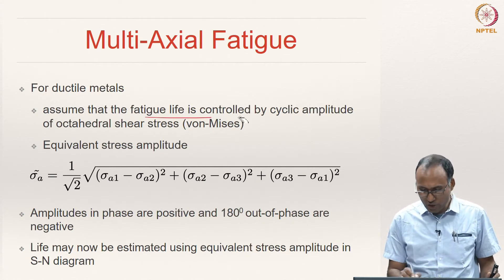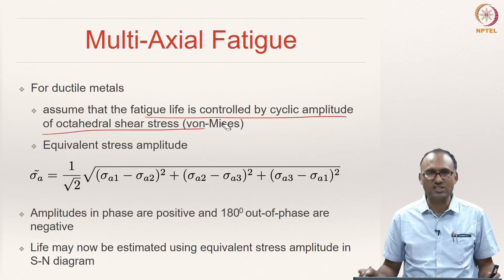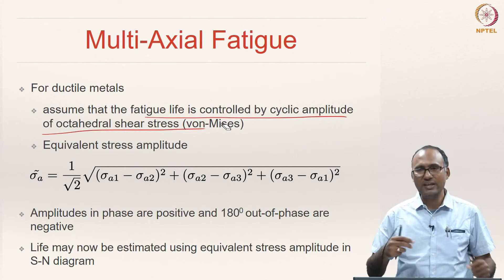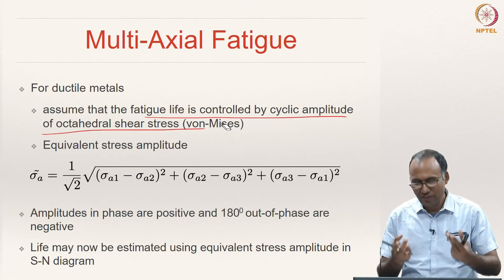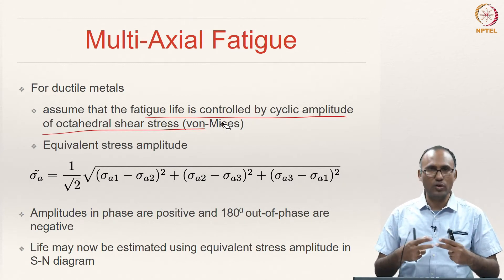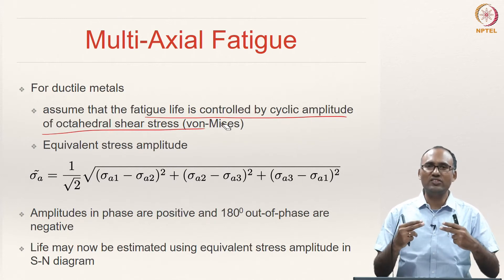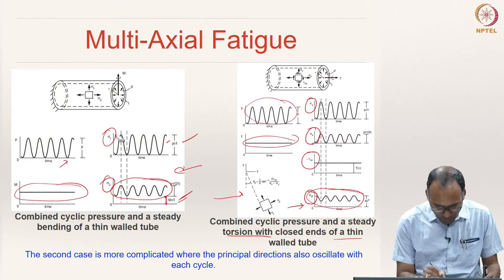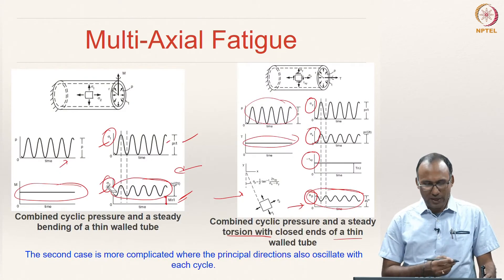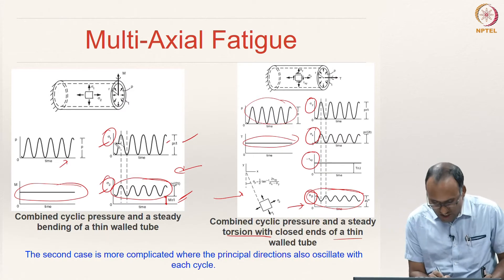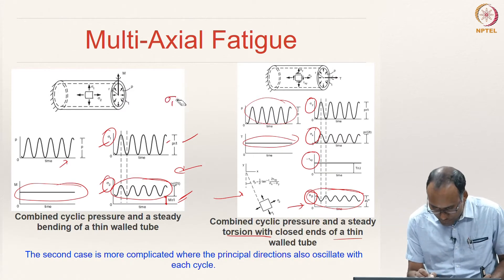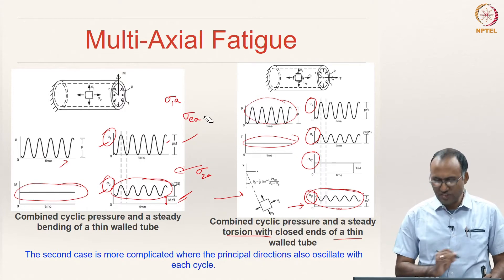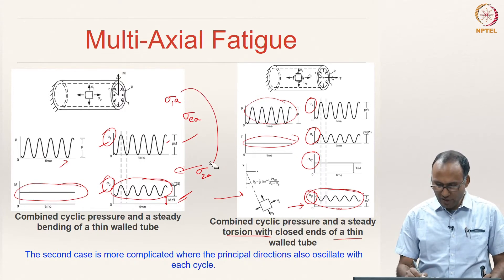You will assume that the fatigue life is controlled by the cyclic amplitude of the octahedral stress. That means you look at the stress amplitude in sigma x, sigma y, tau xy, or whatever components of the stresses are there — all those stresses are actually oscillating. For instance, sigma 1 is oscillating and sigma 2 is oscillating. What you can do is calculate the stress amplitude sigma 1a and sigma 2a, and then calculate the equivalent stress amplitude from sigma 1a and sigma 2a.